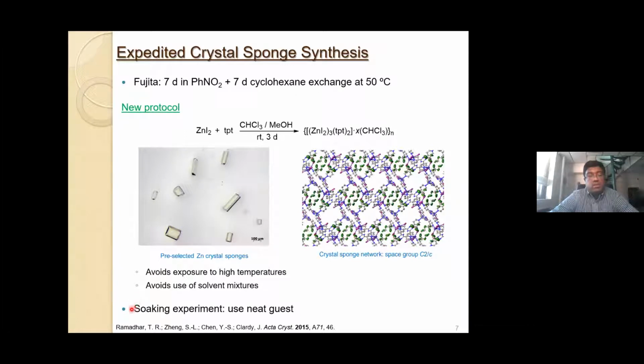And then in terms of the soaking experiment, what I do is I take a crystal, put it in a vial, and add neat guests, so a neat liquid, and add enough to be able to submerge the crystal. This is also done by the Buchwald group at MIT. It's really the easiest way to do this, and you just soak it for 2 days.